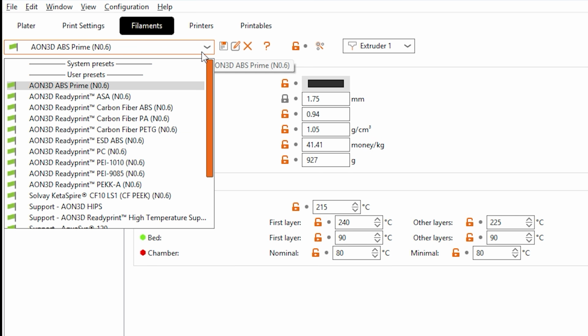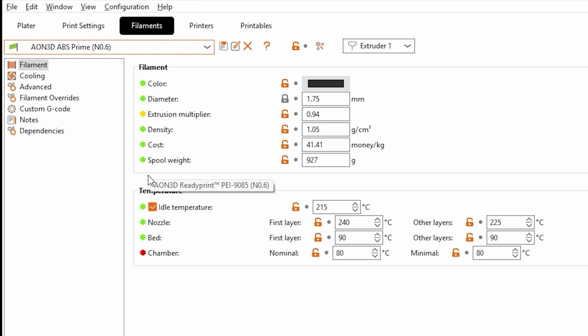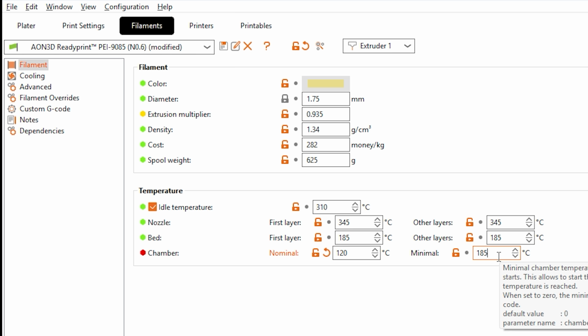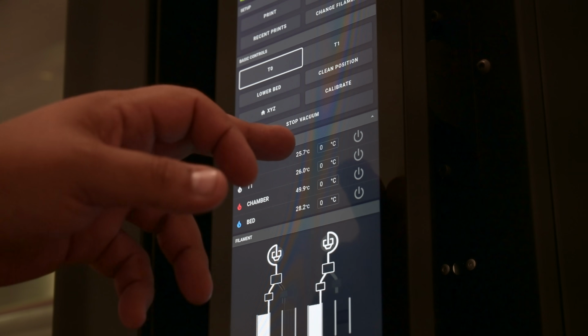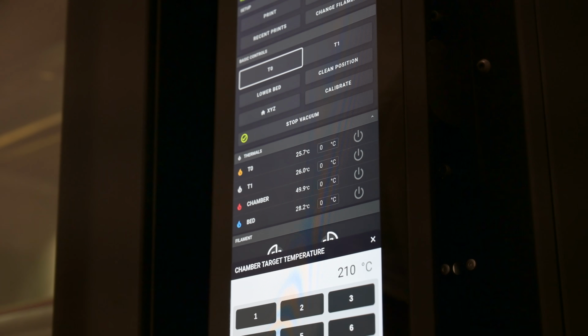To test this was simple. We printed ULTEM 9085 and ULTEM 1010 in a 120C chamber with a 185C bed. Then we repeated the builds at the recommended chamber temperatures. For ULTEM 9085, we recommend a 185C chamber and bed, and for ULTEM 1010, 210C.